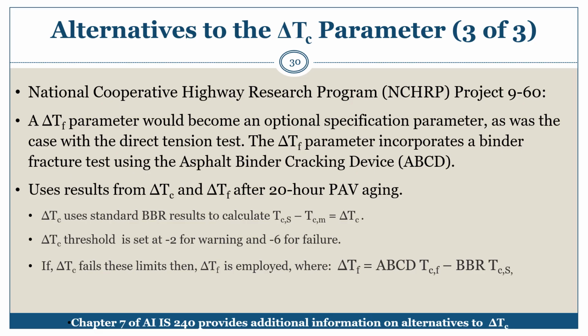Delta TC uses the standard BBR results to calculate T sub c,S minus T sub c,m, equal to delta Tc. The delta TC threshold is set at -2 for warning and -6 for failure. If delta TC fails these limits, then delta TF is employed, where delta TF is equal to ABCD T sub CF minus BBR T sub CS, or delta TF equals the ABCD T critical F minus BBR T critical S.